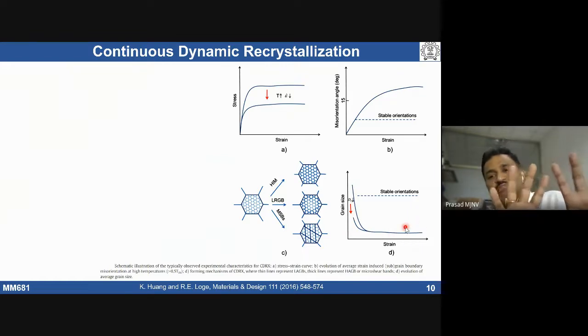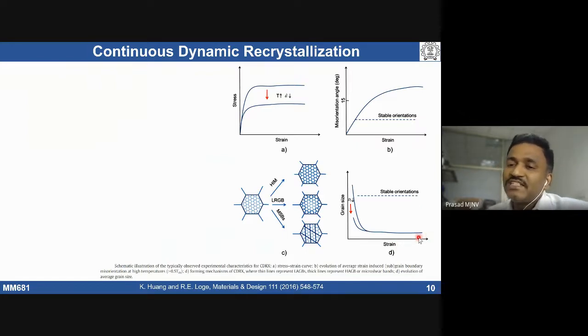Though same material, aluminum. I've given an aluminum, the same material, with only two different grain sizes. One is coarse grain size, the other is fine grain size. When the material is deformed at elevated temperature, where dynamic recovery and dynamic recrystallization are taking place, that leads to the same grain size at the end of the deformation. That means the recrystallized grain that has come from dynamic recrystallization is the same, whether it's a fine grain or coarse grain.